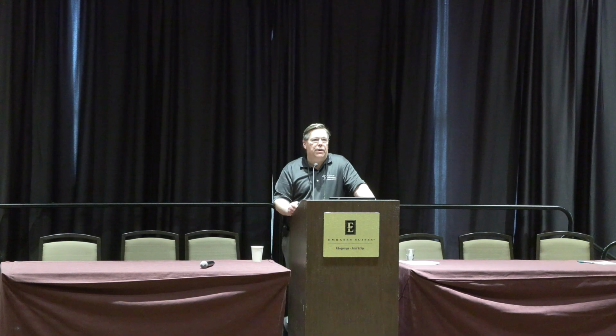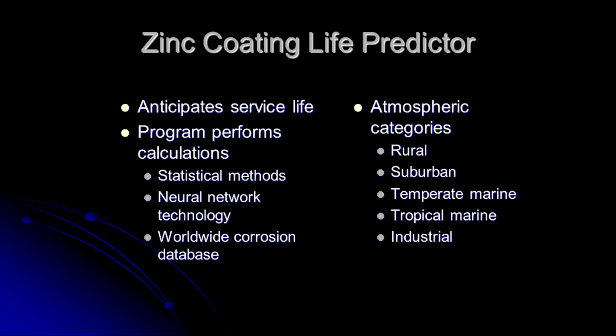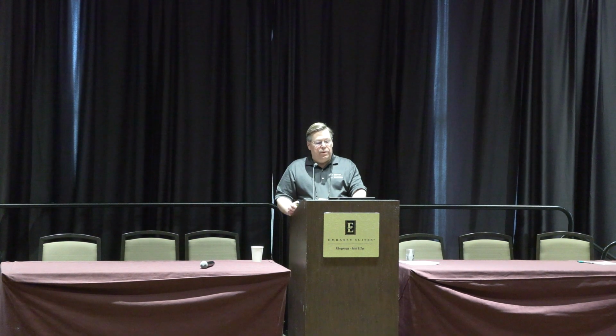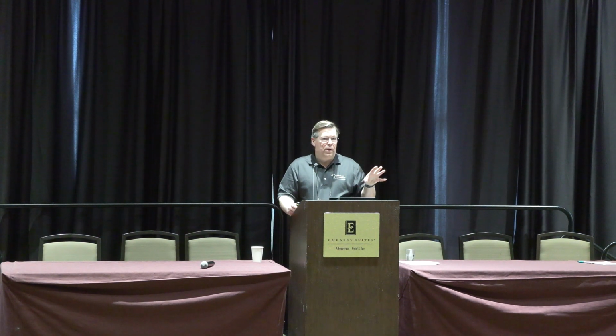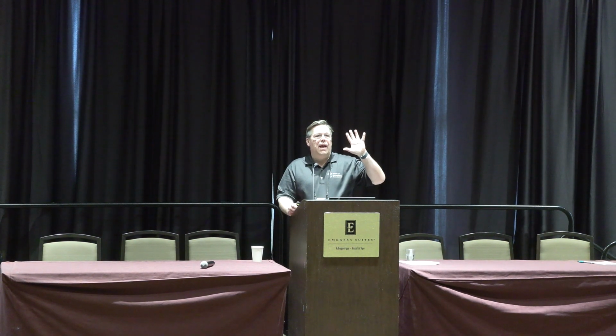This is actually a life predictor that academia did many years ago, and what they did is they looked at all these different environments: industrial, temperate marine, suburban. So if you take a look at that bridge north of Indianapolis in the snow belt in a suburban community, if you take a look at this chart, 3.9 mils in the red should give you about 95 years before you get 5% surface rust. Now, 5% surface rust doesn't mean the zinc coating has failed. What we're saying is the eta layer is gone.